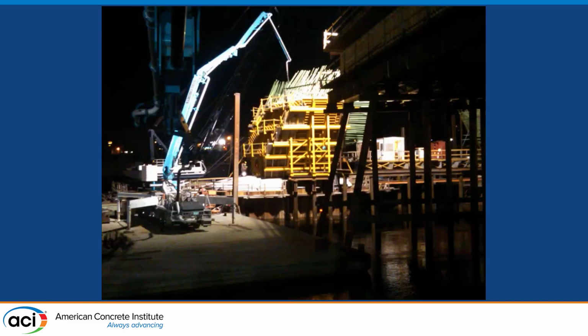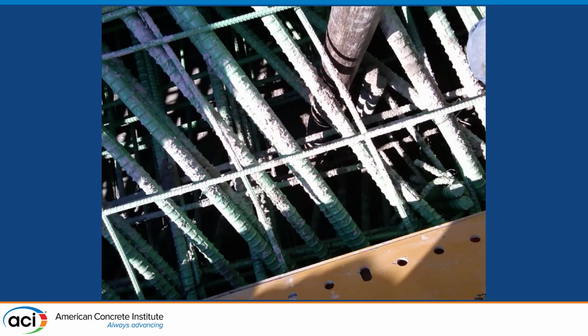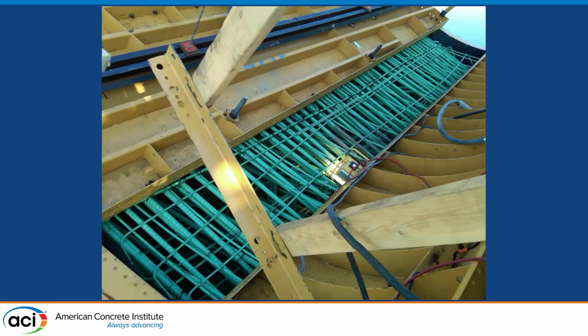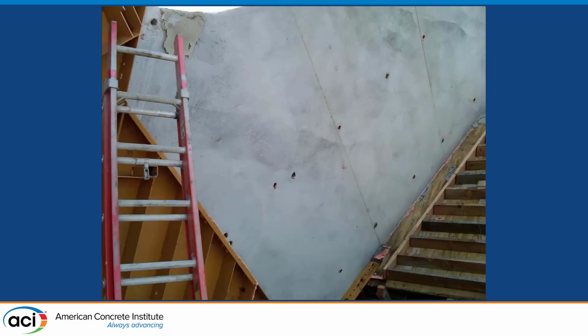This is another small quantity of silica fume containing structure here at Lowry Avenue Bridge, and this is a little bit of reinforcing steel, and it gets placed by leaving the form open to this point, filling it up to this point, and then going on and filling the rest of it. But what's nice is when you use slags and you use these mixtures that the water cement ratio is very low, you can have it pour like Niagara and have strength like Gibraltar.